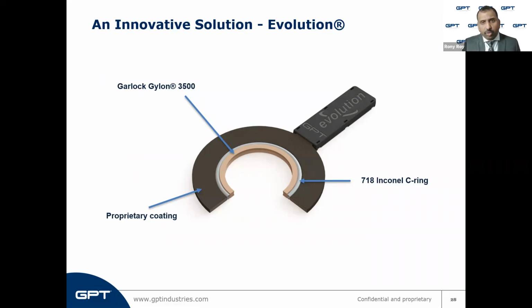This is a 316 SS core gasket with a highly chemically resistant, durable, scratch resistant isolating coating. The ID is sealed by a Gylon 3500, which is a restructured PTFE seal and also highly chemically resistant. And the ID seal is backed up by a secondary seal, as you can see in that cross-sectional view, with a 718 Inconel C-ring that is also coated with a very chemically resistant coating. All coating surfaces are extremely impact and abrasion resistant, and we have subjected them to some severe testing and scratch testing to make sure that they are worthy of being used in the pipelines and in the industry.